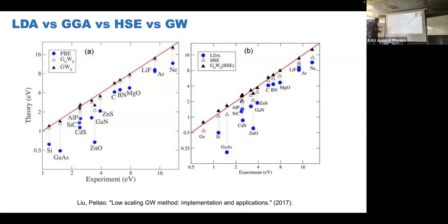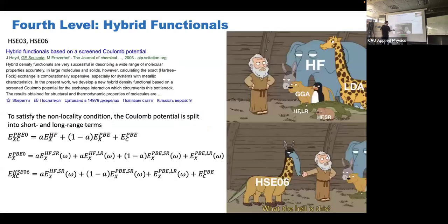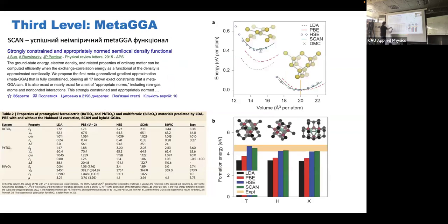So of course we can improve these results by adding some Hubbard parameter on outer orbitals. But it feels like some sorcery, some wizardry. For this trick, you should know the experimental data. If you don't know experimental data, you don't know which parameter you should use in these calculations. Of course, by some tricks we can get it. For example, here you see with U2. So they made this Hubbard parameter U2 just to improve these results.